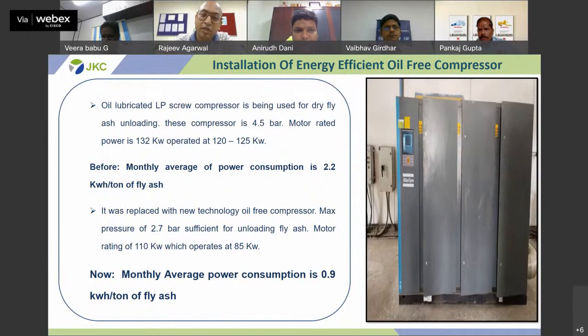Sir, other than this, we have installed energy efficient oil free compressors in our plant. Previously we were using the conventional LP compressor, whose motor rating was 132 kilowatt, operating at 120 to 125 kilowatt. That consumed 2.2 kWh per ton of fly ash for unloading of fly ash. Now we have replaced it with new technology, an oil free compressor. Its maximum pressure goes up to only 2.7 bar, and the motor capacity is 110 kilowatt. This is now consuming 0.9 kWh per ton of fly ash, and definitely this project gives us benefits in compressor power.